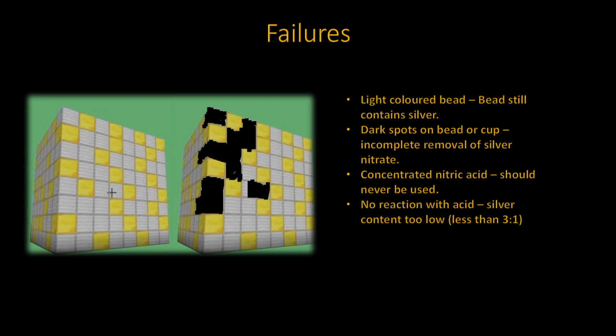During the parting process, if the telltale nitrous oxide bubbles do not appear, and the bead may or may not turn black, it means that the silver content in the bead was too low, and there was no reaction with the nitric acid. Parting will not be complete, and inquartation will be necessary. Now, if that bead turns to a powder, that is, it disintegrates, the silver content was way too high, or the solution during parting was allowed to boil. Caution during decanting is a must. Some of the finer gold may be poured out and lost in the silver nitrate solution.